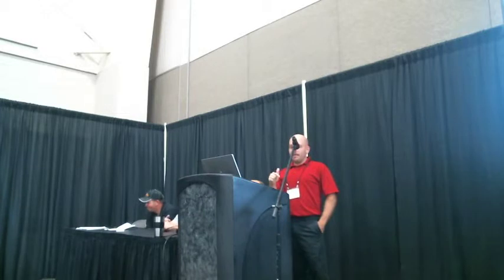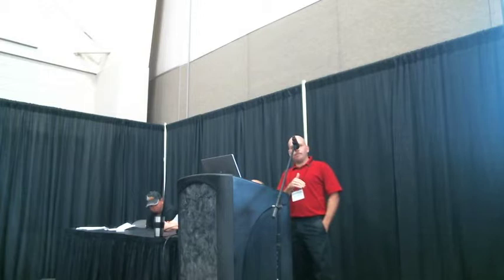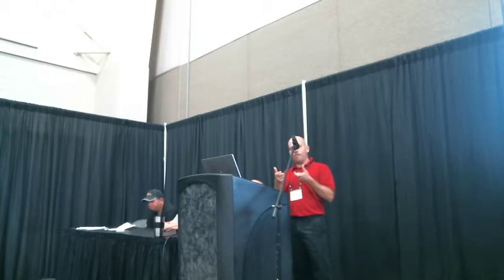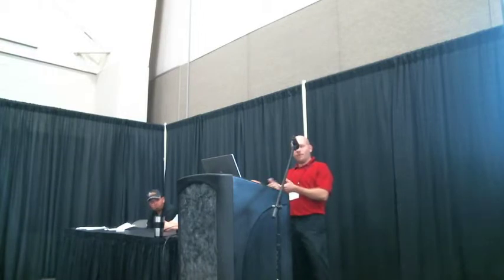But so I wanted a nice stable platform for my concrete. I want a material that is not so strong that it will reflect cracks. That's one of the reasons we went away from lean into HMA, because if I get a really strong base under that concrete and it cracks, that crack will come up through my PCCP. So now I'm in this area, right? I want something strong enough to be stable, but not so strong that it will reflect cracks.